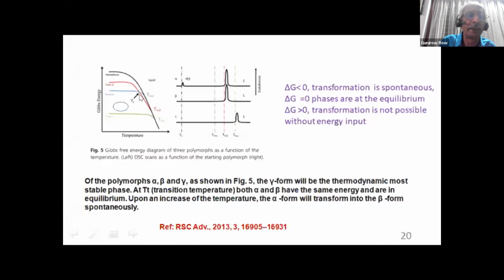So there is a transition temperature T of T. At this transition temperature, the alpha and the beta forms will have the same energy. So they are in equilibrium with respect to each other, and delta G becomes 0. Delta G is 0 for phases which are at equilibrium. Upon the increase of the temperature, the alpha form gets transformed into beta form spontaneously. So the moment we come here, alpha goes to the beta form. You see that these two are very close to each other. So alpha goes to the beta form, which is the next stablest form.